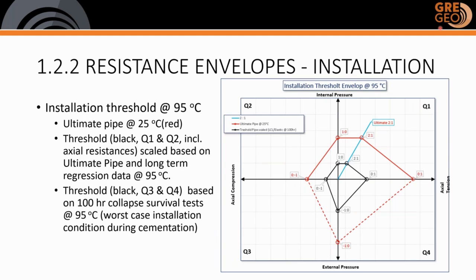If we then look at the threshold envelope, that's the black one you see over here. The black 2.1 point you see over here is based on long-term pressure tests according to ASTM D2992 at 95 degrees C. This provides the regression gradient and the lower confidence limit. The lower confidence limit is also indicated as hydrostatic design base. The black 2.1 point is also verified using a 100-hour survival test based on the regression gradient and the LCL value.